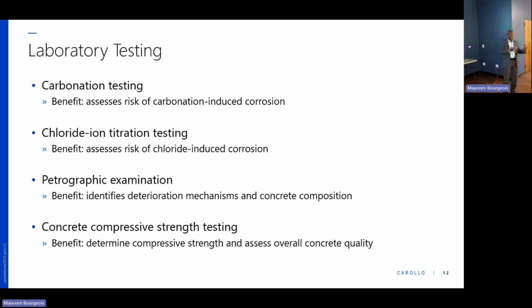For these structures, the existing drawings were available to us, so it was really good. We're able to verify. The minimum on the drawings that we were able to look at was 4,000 pounds per square inch. So compressive strength is measured in pounds per square inch. So you take the core and then you measure that. And then we are going to see what the results show when we tested our cores. So with compressive testing, we get the compressive strength of concrete, and it tells us overall what the quality of the concrete is, and if the structure still has the strength that it needs.